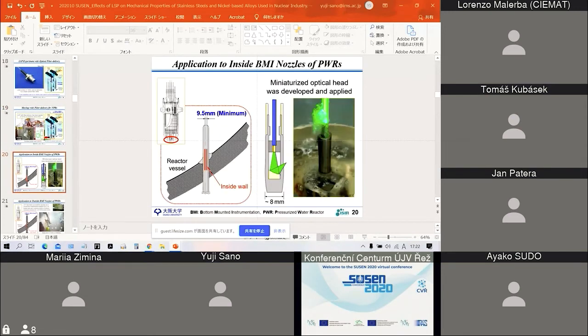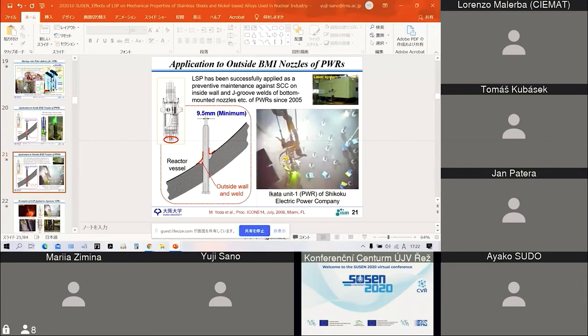So we also applied laser beaming to pressurized water reactors. In this case, the BMI nozzles. BMI means the bottom-mounted instrumentation. So we developed a pencil type of very thin optical head like this, and this one is the basic experiment. And we peened the inside of such pipe and actually applied it to the nuclear power reactor PWRs, to the inside wall of the BMI nozzles. And also we applied the laser beaming to the outside wall and this weld by LSP like this. So we did actually apply laser beaming to PWRs since 2005.